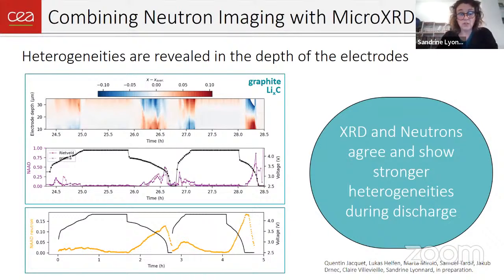And the main results that we can say from this data, without going too much into detail, is that first of all, the strongest heterogeneities develop during the discharge. And the faster you cycle, you see the discharge here is faster, the higher the heterogeneities are, as you can see from the color code.